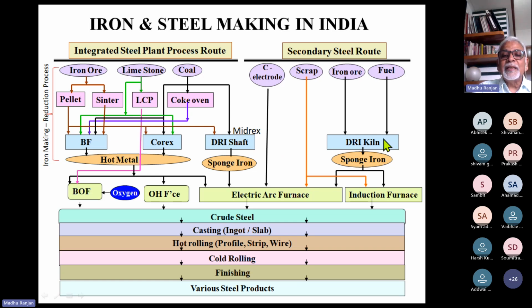These iron making processes depend on raw materials such as iron ore, in lump sizes. The fines of the iron ore have to be agglomerated in the form of pellet or sinter. Then the iron ore also contains some gangue content or impurities. To take care of them, some fluxes are required, which is limestone here. And the fuel here is the coal. Part of the coal is a coking coal variety, which makes coke for blast furnace. But COREX and other methods of iron making do not require coke.